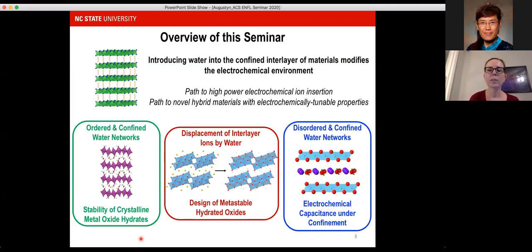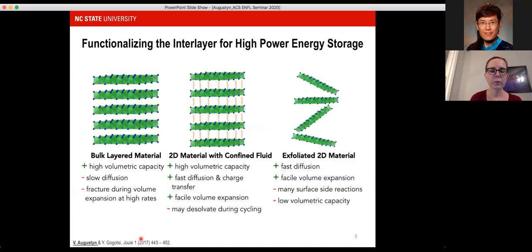And the third is how disordered and confined water networks lead to electrochemical capacitance under confinement. So the intercalation process looks very different when you have disordered and confined water networks present. A few years ago, I co-authored this perspective that hypothesized about what we could obtain if we functionalized the interlayer for high power energy storage.